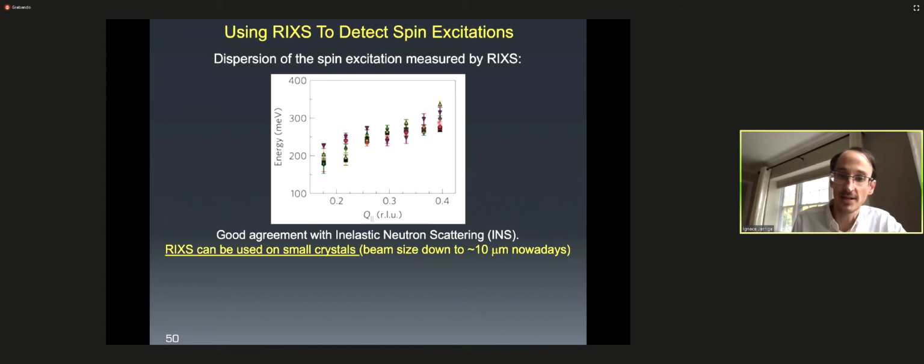That dispersion is a characteristic signature of a spin excitation. And again, it is showing that even in a superconductor, you have a local spin wave forming. It may not be long-range order at the macroscopic scale, like a strong magnet, but locally, within a few unit cells or maybe a few tens of unit cells, you still have a local magnetic order in the superconductor.